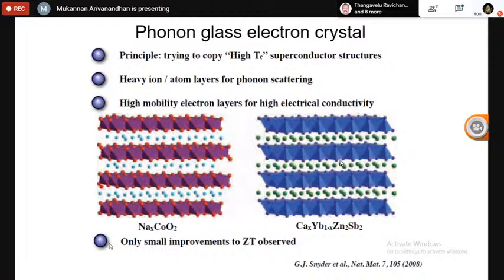And how do the phonon glass electron crystals look like? So most of the layered materials, like the high TC superconductor materials, are a highly complicated structure with multiple components. And once if you have such kind of multiple components with the complexity in the structure, that will lead to increase the randomness in the system, and that will have some kind of effective phonon scattering, as well as due to its high electrical conductivity, it should have some kind of electron transport. So once if you have that kind of high TC based structures, then you can have the reasonable phonon scattering as well as the smooth electron transport.